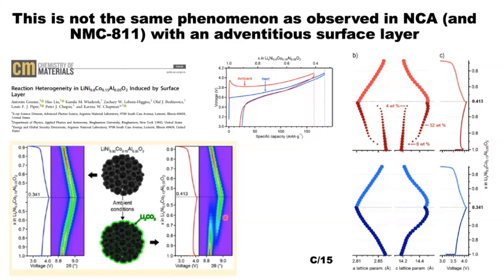And there you really will see this two-phase material because of the impedance associated with getting the lithium through the lithium carbonate. And this two-phase process disappears if you look after your materials well, or after the first and second and third cycles where you remove the carbonate electrochemically.